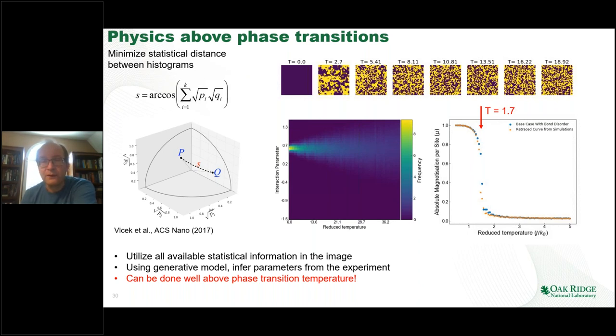There are very few liquid helium microscopes. So if I can measure the physical behavior at temperatures well above the phase transition, I simply have more opportunities to do so. Of course, this doesn't come without a price. For example, we can do the uncertainty quantification, and we show that the higher the temperature, the less reliable your method is, but that's kind of expected. There is no free lunch.